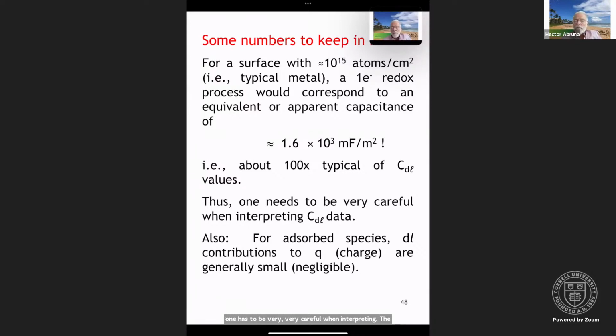So one has to be very, very careful when interpreting the double layer capacitance. So it's a question: is it reasonable to assume 1 adsorbate molecule per atom on the surface? Organic molecules can be big, absolutely so. But for example, if you take something like carbon monoxide on a platinum surface, it's 1 CO per surface platinum atom. Obviously, if you have a larger molecule, then it will be a lower surface coverage.